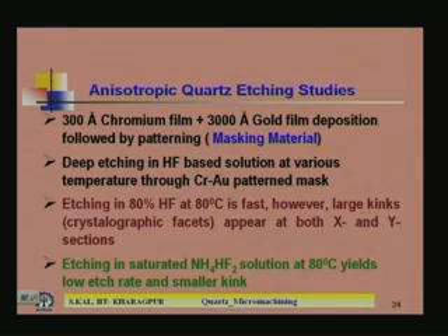Okay. Now, the anisotropic quartz etching, what are the materials you use? Chromium gold is used as a masking material, 300 angstrom chromium film, 3000 angstrom gold film, followed by patterning, you will get the masking material. Deep etching in HF based solution at various temperature through chromium gold pattern mask. Okay. What is then the etching solution? Hydrofluoric based solution is the etching solution. 80% hydrofluoric acid at 80 degree centigrade is fast. However, large kinks and crystallographic facets appear at both x and y sections. So, some crystallographic facets will be created, and those facets will create some problem in your structure.